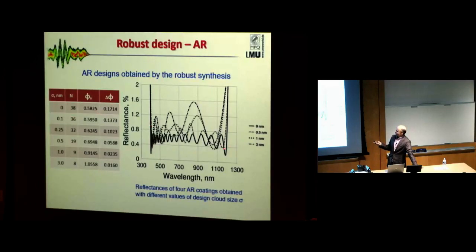Let's say you can provide a very complicated anti-reflection coating with nice performance. It has 38 layers and a very small merit function. But actually, it's very difficult to produce such an anti-reflection coating. If we include our error bars in our structure, our layer structure becomes much simpler. Our software just tells us we cannot produce a very complicated coating. It makes no sense to design a 38-layer coating if our precision is 3 nanometers. It means the software gives you a design with 8 layers. The properties of this design are worse, but you can be sure that you're able to produce this layer structure.